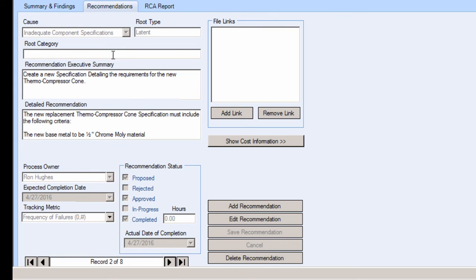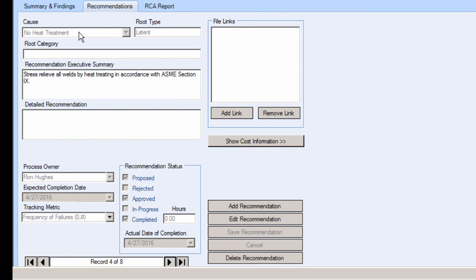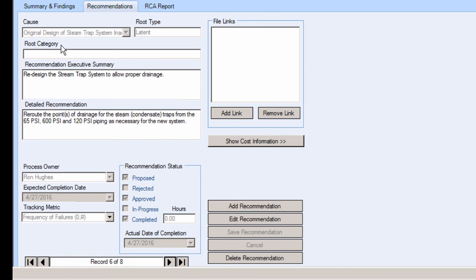Inadequate component specs, a latent root cause. We're going to create a new specification detailing the requirements for the new thermo-compressor cone, and we give all the detail for that. No requirement for weld inspection. We're going to add necessary weld inspection testing requirements and the detail for that. No heat treatment. We're going to stress relieve all welds by heat treating in accordance with ASME Section 9. Drains impeded by back pressure. This is a steam trap system. We're going to reconfigure the design of the steam trap system to remove back pressures that are preventing adequate drainage.